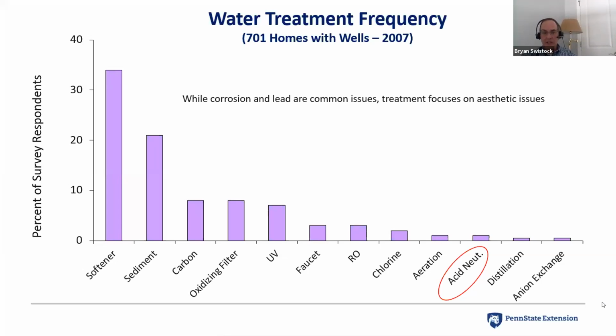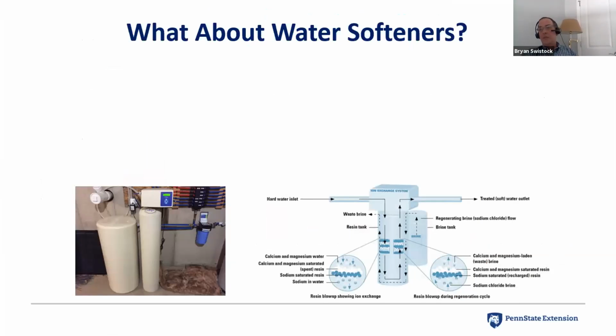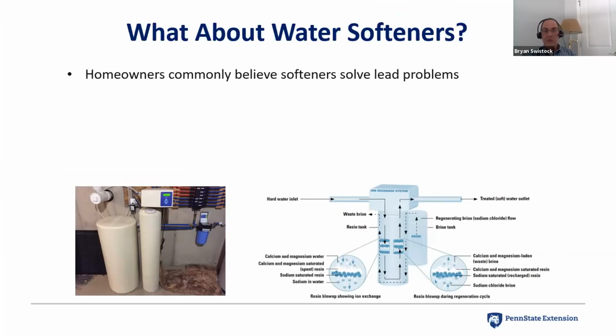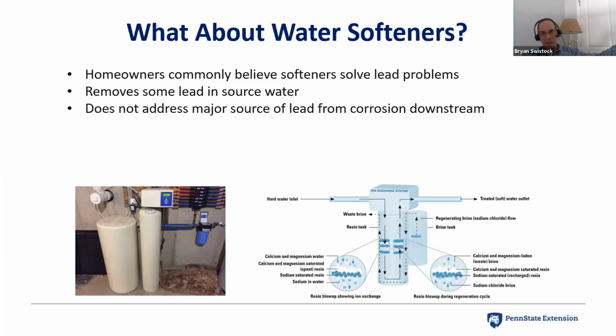concerns. You will notice things like RO units are a little bit more common, and also faucet filters, which tend to be carbon filters, as well as larger carbon filters, are more common, thankfully, and those will help to deal with some of the lead problems. We get questions all the time about, well, I have a water softener, so I don't have a lead problem, because water softeners take everything out. Well, softeners do a lot of things, and homeowners definitely believe that they will remove lead, and they will remove some lead. They're a cation exchange device, and lead is typically a cation. So you can get some lead removal from source water, but the problem is most of the lead's coming in after you would put a softener in anyway. So it doesn't address that major issue with corrosion of lead.